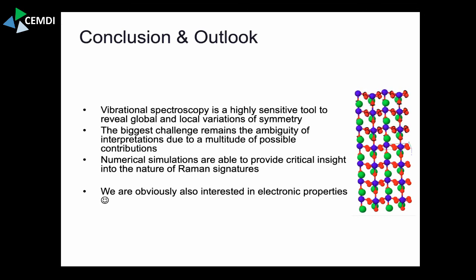Yeah, it's DFT based. So in principle, if you want to get first information on the Raman energy, what you do is you simulate the interatomic bond. You go to the minimum energy, to the equilibrium distance, and you make perturbation theory around that one, harmonic approximations, you get the phonon energy. And so that would be the energy. And to get the intensities, well, you need to calculate the change of electronic polarizability. And that is still classical non-resonant Raman.